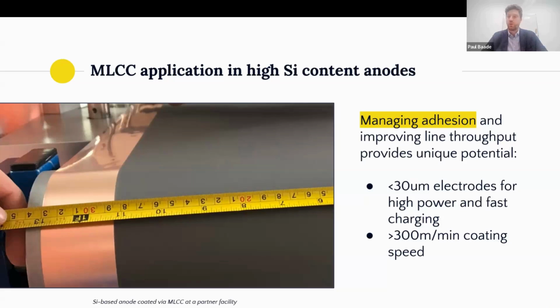If you have a good quality material with silicon anodes, that means your current coating line is actually underutilized. With that kind of loading, you can actually increase coating speeds a lot. You have an existing dryer length that was meant to handle wet loadings of maybe 200-300 grams per square meter. Now with an increased capacity material, you only have to handle 100 grams, so you can increase coating speed. And this is where the curtain part of the multi-layer curtain coating actually comes into play, because the curtain, as I mentioned in the very beginning, actually has a pressure impact once it hits the substrate. And that pressure hitting the substrate allows you to go to coating speeds much higher than 200 meters per minute.